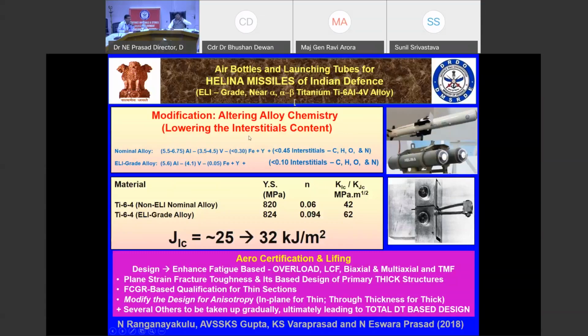So we were trying to take titanium alloy, which has this nominal composition, and the properties are 820 yield strength, and it has a very little fracture toughness, 40. Let us compare this 40 value. I'll not talk about complicated numbers like fracture toughness. The maraging steel has 100, 120. So for the HELINA to qualify, it needs a minimum fracture toughness of 55 plus. When we did an alloy design, what we could do is reduce the interstitials in the titanium alloy, Ti-6Al-4V, in terms of carbon, hydrogen, oxygen, and nitrogen. We reduced its total content from 0.45 weight percent to less than 0.1 weight percent.